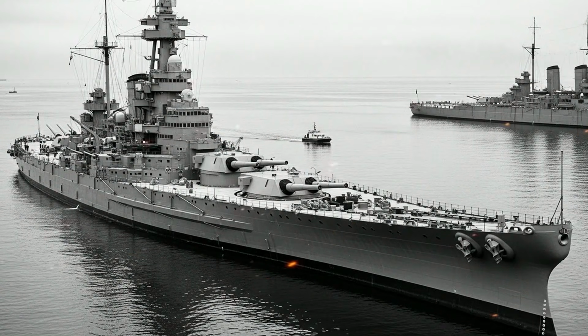the ship's primary weapon. The Philadelphia trials in November 1942 tested sample plates from all three manufacturers against Mark 8 shells at various ranges and impact angles. The results confirmed what calculations had predicted. At ranges below 25,000 yards, Mark 8 shells penetrated the 12.1-inch Class A armor with disturbing regularity when striking at angles simulating belt impacts. The 19-degree slope helped somewhat, but not enough.